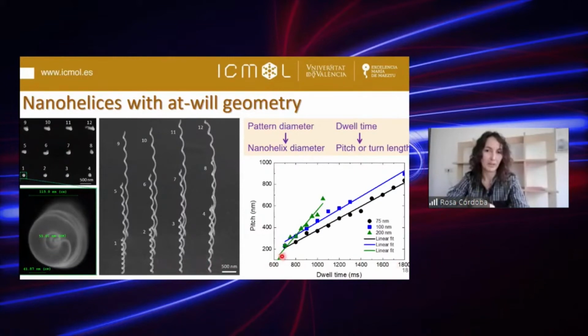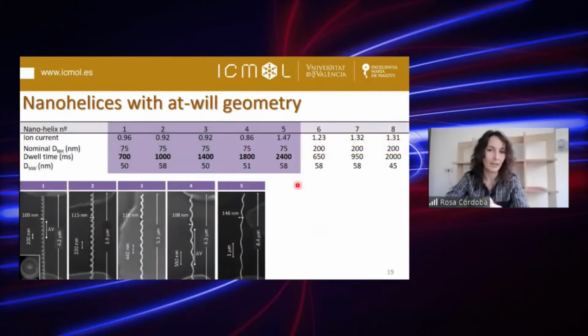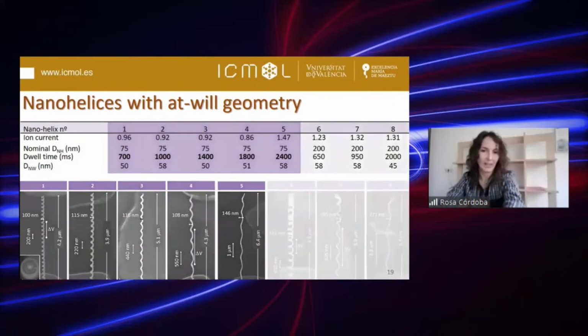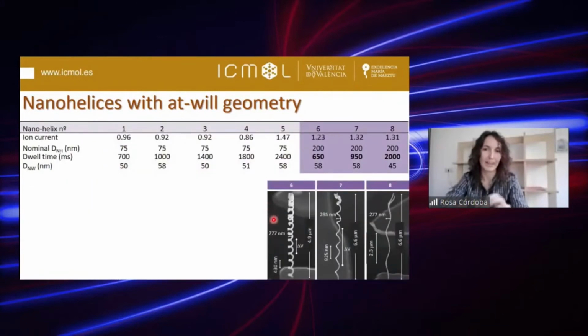So just modifying the dwell time, we can tune the length of the turn from 200 nanometers to at least 900 nanometers. So here I show a few examples. I was trying to maintain the diameter of these nanohelices around 100 nanometers and modifying the length of the turn from 200 nanometers to 1 micron. And you can see how these nanohelices look like and the length of each one, which was in the microscale. On the other side, I was trying to keep the diameter of the nanohelix around 250 to 300 nanometers and the length of the turn from 430 nanometers to 2.3 microns.